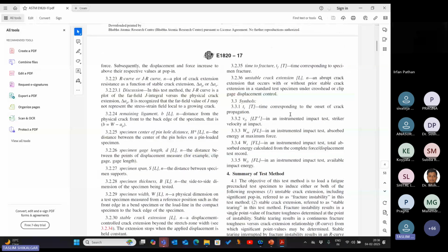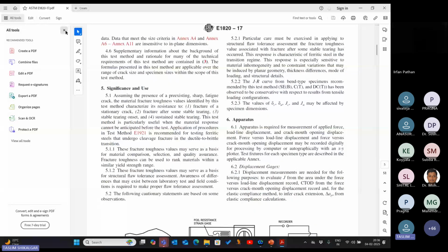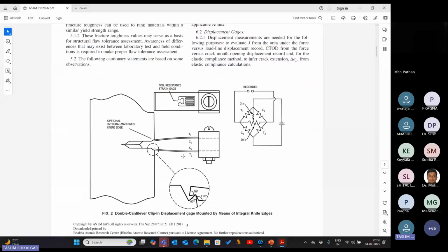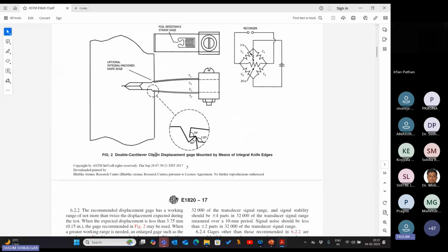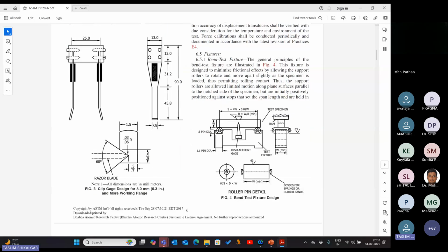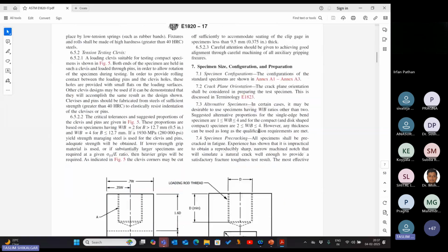I'm just going below so I can tell more about the specimens. Here you can see they use this gauge to find the crack mouth opening displacement. Generally, people use load versus displacement data, applying displacement here and load here, so they calculate global load versus displacement. But in this approach, they are not calculating the displacement of the specimen. They are calculating the displacement of the crack: how much is the crack opening. And they plot the crack mouth opening displacement versus the load. Here they show how we can utilize this.